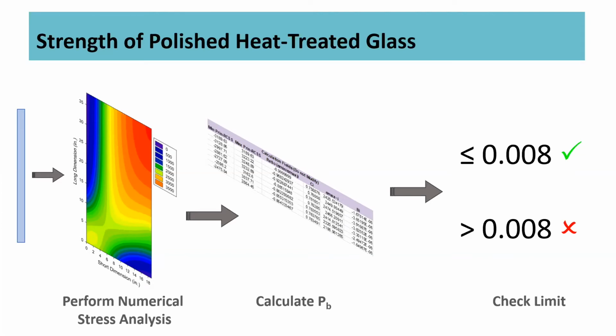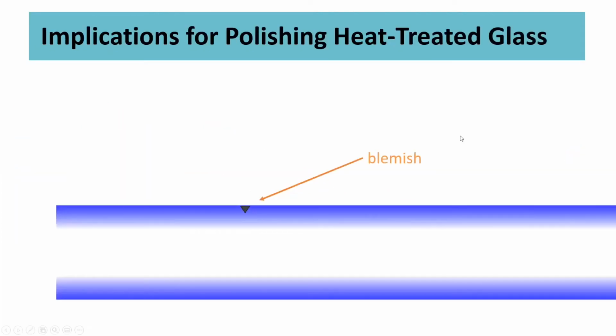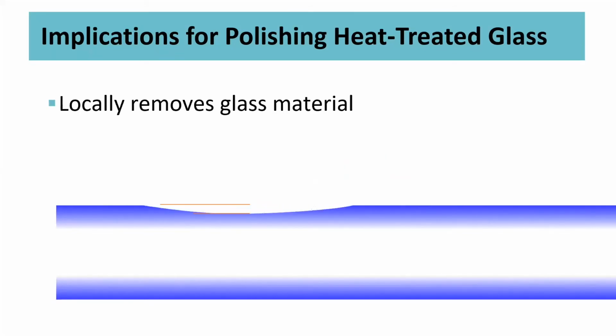So moving forward, when we polish glass, so we have this blemish, when we polish heat treated glass, what's going to happen to the glass physically? So we need to understand that. So one thing is that we immediately recognize that we're removing glass material. So the thickness of the glass has changed in the area that we polished. Now, in many of the projects that Mark and I have worked on, typically the places in the glass that need to be polished is not the entire surface. Mark showed one of his examples where it was effectively the entire surface, but usually it's in some smaller location at a particular point on the glass.